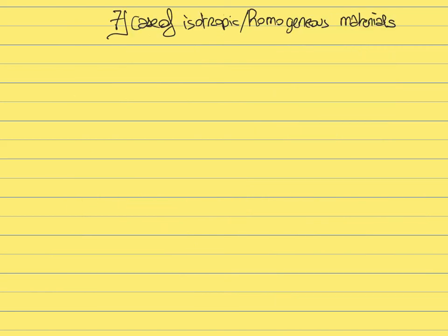So far we have defined three types of elastic properties that describe different types of elastic behaviors of materials. The Young's modulus, which characterizes the elastic resistance to normal deformation, the shear modulus, which characterizes the resistance to shear deformation, and the Poisson's ratio, which describes the Poisson effect, that if you elongate in one direction, it's going to shrink in the other, and vice versa. So one thing is that all those three elastic properties are not independent from each other. They are related to each other.